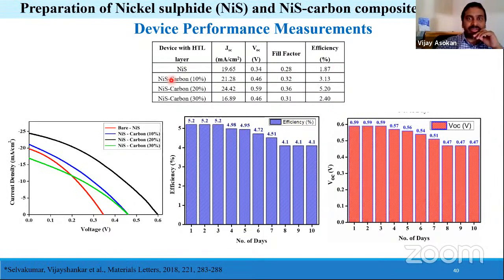Here, if you keep on looking, compared to nickel sulfide, with nickel sulfide and carbon the efficiency is increased, then efficiency keeps on increasing, then the efficiency is decreased at some point when we keep on adding carbon, because when we have carbon within the composite materials, there are many surface pores which can effectively be used for charge carrier mobility.